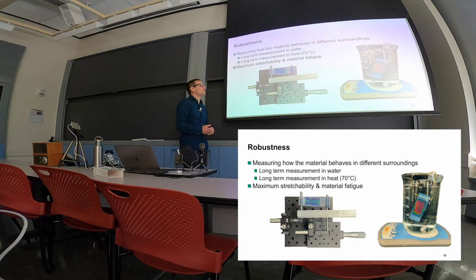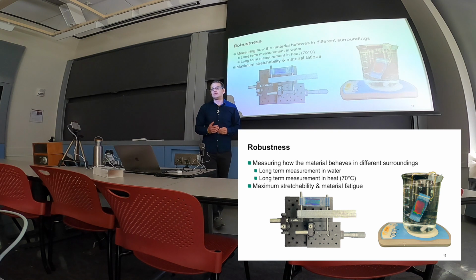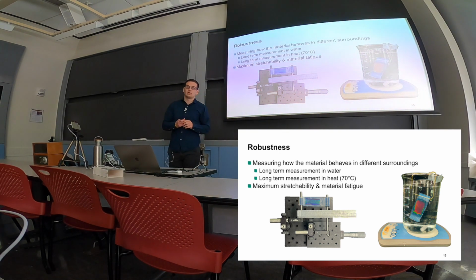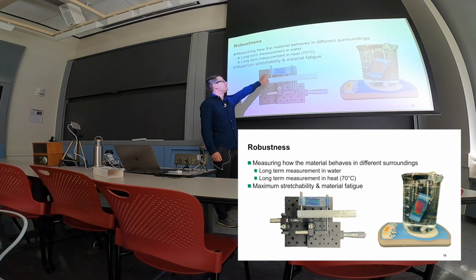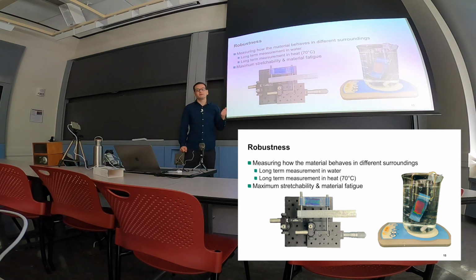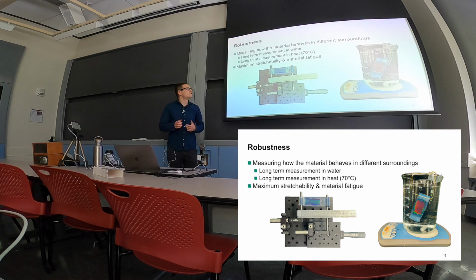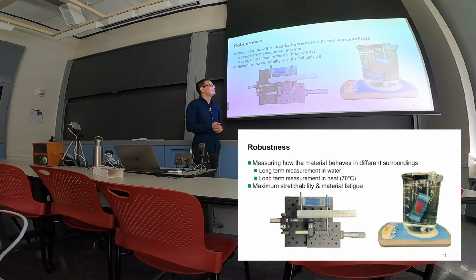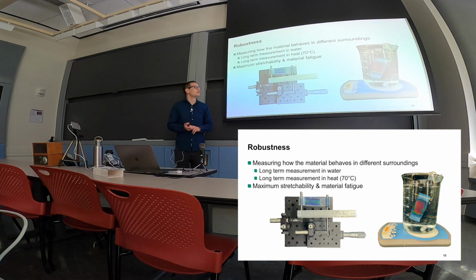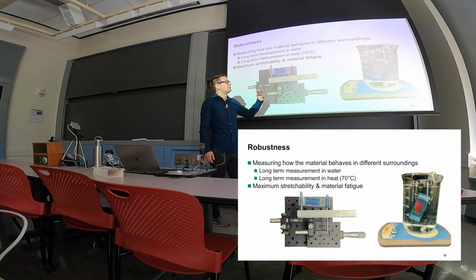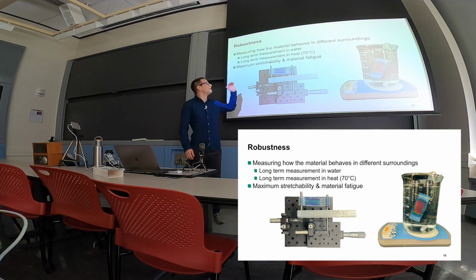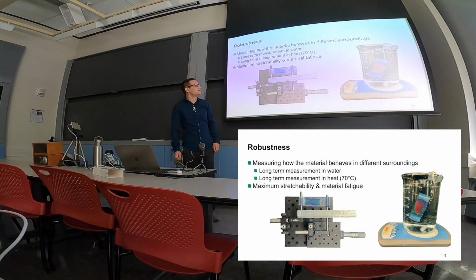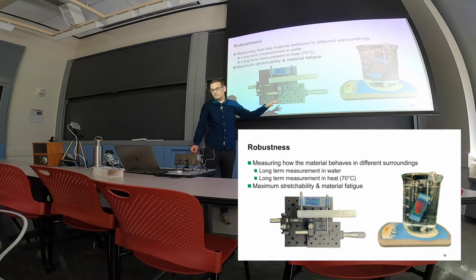For the robustness, I wanted to test the materials and the 4-layer approach in a more harsh environment, where I set this color changing material with the soft robotic system once in floating water over a course of 8 days, once in an oven at 70 degrees Celsius, and once just in the lab, so a reference sample without another temperature and another humidity, and then observe how the spectrum changes over a course of 8 days. And I also wanted to do a maximum stretchability test, as we can see with the device here on the bottom left side.